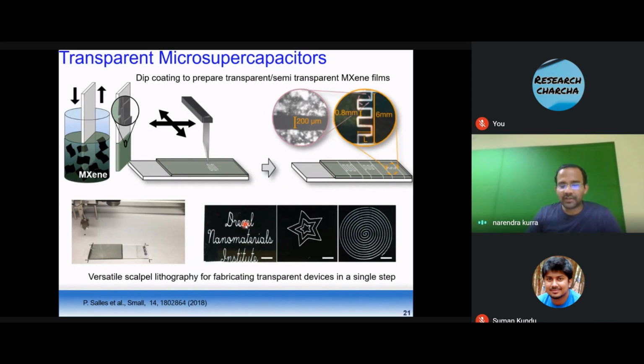And one of the techniques we developed at Drexel is called the automated scalpel. So we obtain transparent MXene coatings by the dip coating method. This is an MXene colloidal solution; glass was dip coated in this colloidal solution to make semi-transparent coatings, followed by engraving using a scalpel method to make these interdigitated electrodes. If this thin film had to be taken through the photolithography process, probably at the end of the photolithography we may not end up having this film, or the intrinsic properties might be affected by the residual photoresist. This is where direct write techniques have a unique advantage to faithfully retain the intrinsic properties of MXene films for energy storage, transparent energy storage applications.